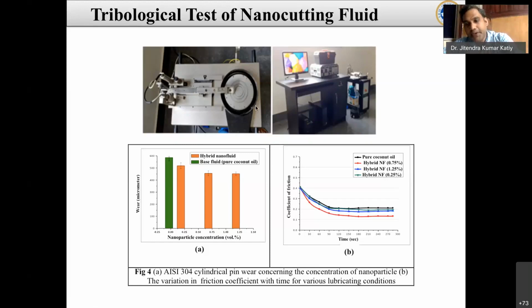One reviewer asked this question: why did you choose the aluminum pin with the EN31 steel disc? Why have you not chosen titanium, with the same environment that you want to use in the turning? The answer I gave, and this reviewer was also satisfied, is that I observed in several literature sources that if we use a titanium pin, the seizing problem in the titanium pin is very high, because it is very hard. So seizing is not done in the titanium one. Because of that reason we have not chosen it, and it is also not recommended by other reviewers.